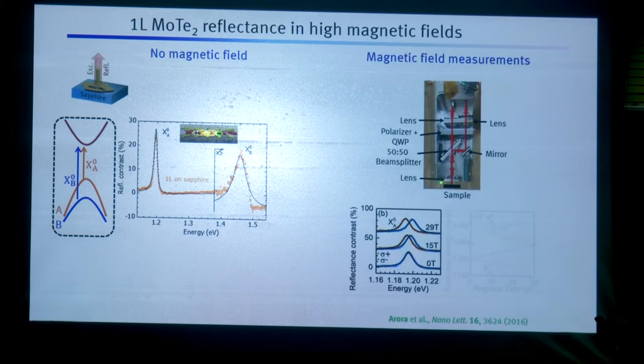Now, if we have to apply magnetic field, we have to take this sample to 30 Tesla in liquid helium. And in 2010 in TIFR, I had experience of building such probes. So I just replicated that experience, built a probe, and to measure the reflectance spectrum, we put the sample down in 30 Tesla magnetic field at 4 Kelvin. And immediately we see the splitting or Zeeman splitting of lines.